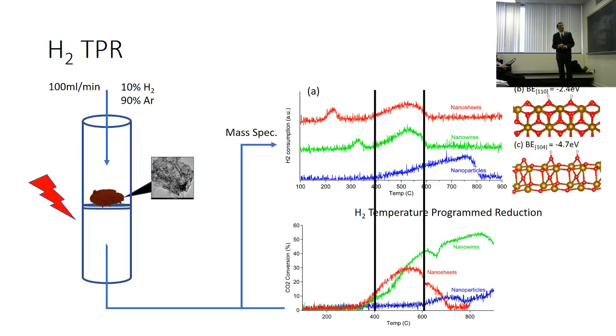The second thing we have to look at is this pre-peak. What does this pre-peak mean? When you have a peak, it means reduction is occurring. If you look in the literature, people don't do reverse water-gas shift with hematite, but they do it with